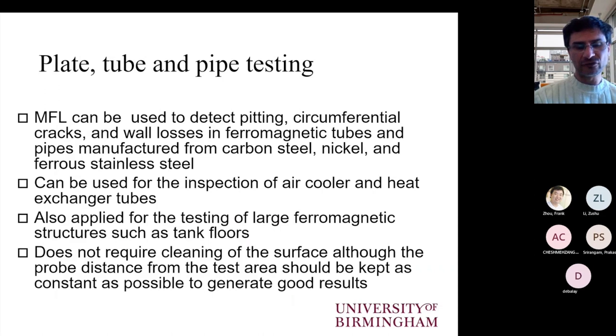Now, what are the applications where we typically use magnetic flux leakage? So we tend to use it on plates, tubes, and pipes. And of course, all of these components have to be ferromagnetic, so they have to be typically made of carbon steel or carbon manganese steel in order to enable the magnetization of these components. Nickel and ferritic stainless steel grades are also inspectable with magnetic flux leakage.